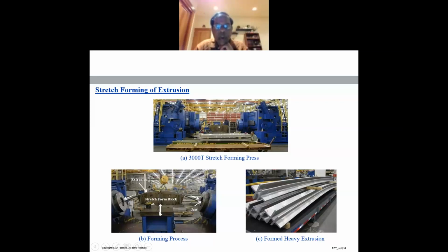That's the stretch forming block, where the extrusion is being stretched to get the contour of the stretch form block, because every part has its own geometry and the precision tolerances to be maintained by the process. So that's why the stretch form block has to be very accurate. The extrusion is clamped between the two clamping jaws and stretched, and the forming block moves up to give the permanent deformation of your extrusion at the end of the forming.